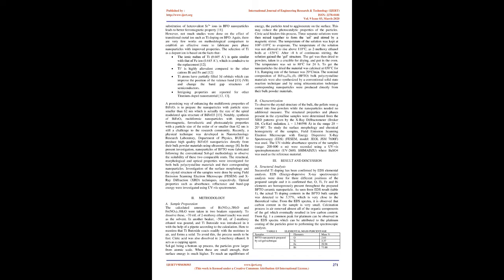Although the ferroelectric properties of BFO have been studied, its other properties like moderate bandgap, 2.2 eV, appropriate band edge positions, stability, and non-toxicity indicate its suitability as a photoelectrocatalyst for water oxidation. BiFeO3 is, however, difficult to put into application due to its low resistivity, and the synthesis of the pure phase is intrinsically difficult. Some improvements in the methodology of synthesis have been studied to reduce formation of impurity phases. 5, 6, 3.